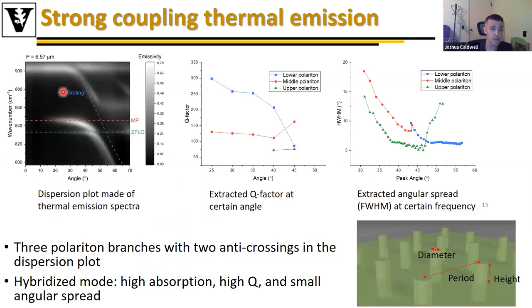And what you see right here is that three-way strong coupling shown here, where basically this is a 7-micron grating with about a 1.5 or 2-micron diameter pillar. Sorry, I don't remember off the top of my head, with about a 1-micron tall pillar. You can see a rough schematic of the structure here. And as I tune the angle, I can measure the thermal emission intensity.